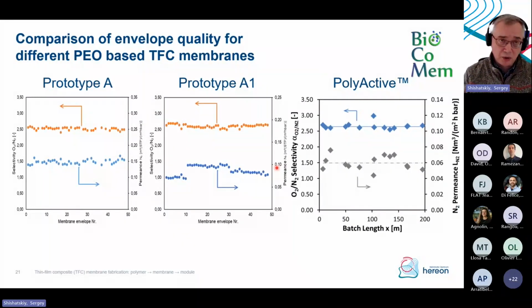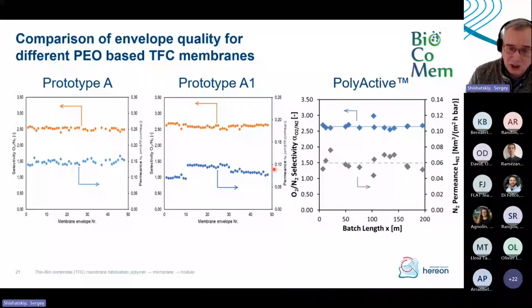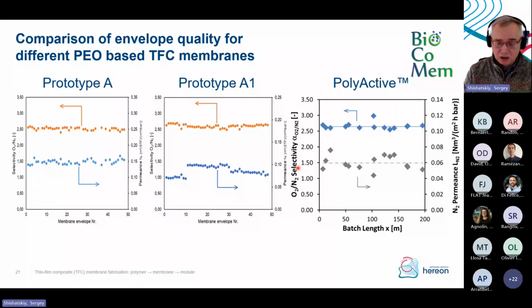That's a good indication, because then we have two proofs of membrane quality: by electron microscopy and the corresponding value from envelope investigation. Oxygen nitrogen we use because we just press air through the membrane, and then we observe what concentration of oxygen is on the permeate side. And this is the first real exposure of the membrane to the mixed gas feed stream. And we can judge from this investigation what the membrane quality is. This is quite a good number.